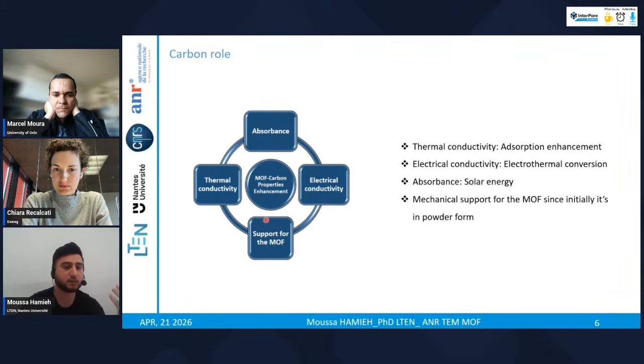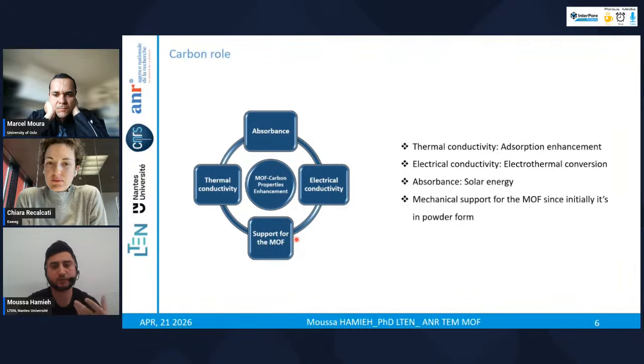And finally, it provides a support for the MOF, since the MOFs are initially in powder form. So with the carbon, they can be shaped into pellets or plates or whatever you want. So it will provide the mechanical support for the MOF. As we see here, combining MOF with carbon material allows us first to manage the thermal effects during the adsorption and opens the way to renewable energy sources for regeneration, with low energy cost for the step of desorption.